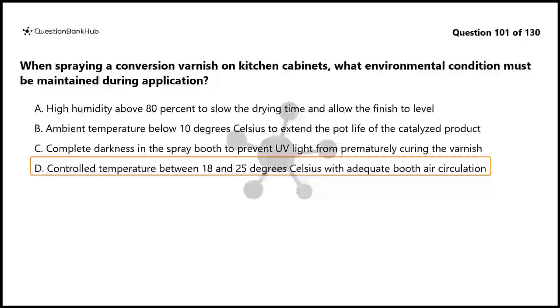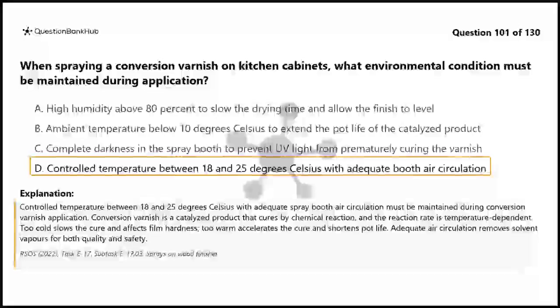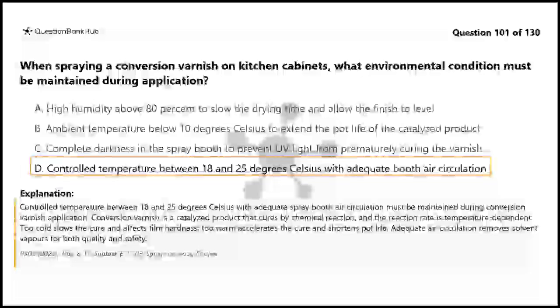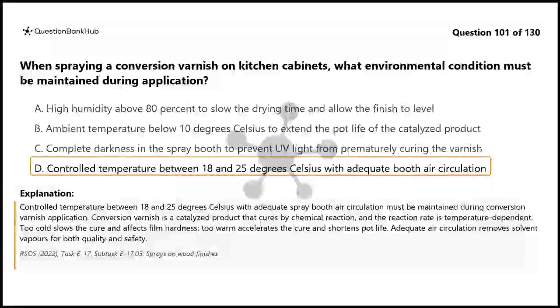The correct answer is D. Controlled temperature between 18 and 25 degrees Celsius with adequate spray booth air circulation must be maintained during conversion varnish application. Conversion varnish is a catalyzed product that cures by chemical reaction, and the reaction rate is temperature dependent. Too cold slows the cure and affects film hardness, too warm accelerates the cure and shortens pot life. Adequate air circulation removes solvent vapors for both quality and safety.